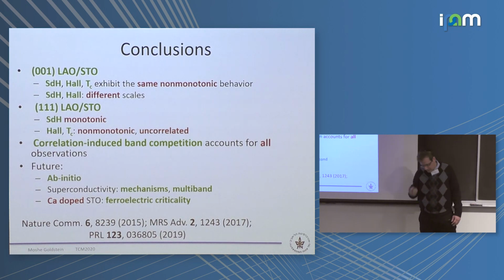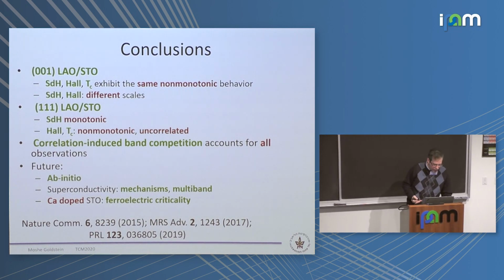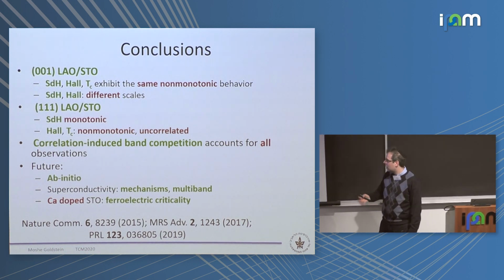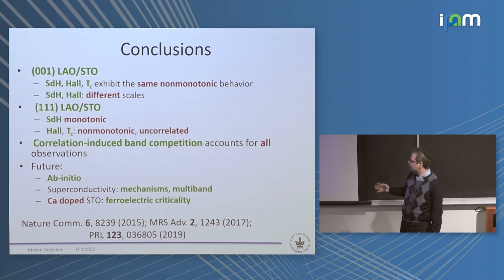So to conclude, we have seen studies of 001 and 111 LAO STO. In the first one of them, all properties that were measured were non-monotonic with peak at the same place. In 111, Shubnikov is monotonic, the others are not monotonic but not correlated. And if you invoke a simple model of bands which compete among themselves because of repulsion, you can fill one but maybe not the other, then it nicely accounts for what happens in the two materials. In this one, there is a big difference in effective masses, so population is transferring between the bands, causing non-monotonicity in all quantities. In this material, it is not happening, so Shubnikov is monotonic. Other properties are not, but this is due to particular reasons, not because of this effect.